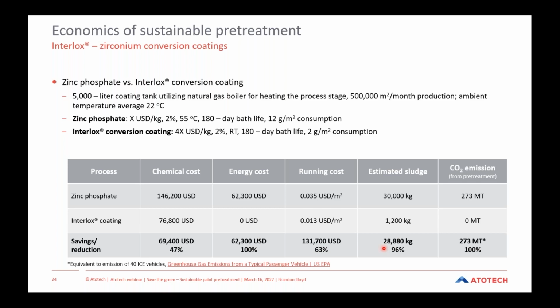Looking at the estimated sludge or byproduct that is generated from the process itself, with the zinc phosphate process, we can typically see in such a scenario about 30,000 kilograms per year from the process, and with the interlocks process, greatly reduced by about 96%.